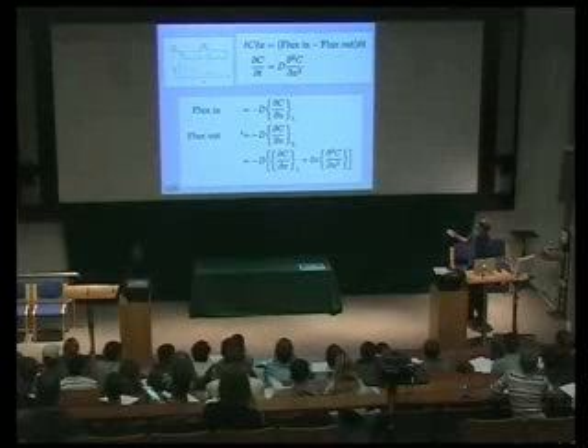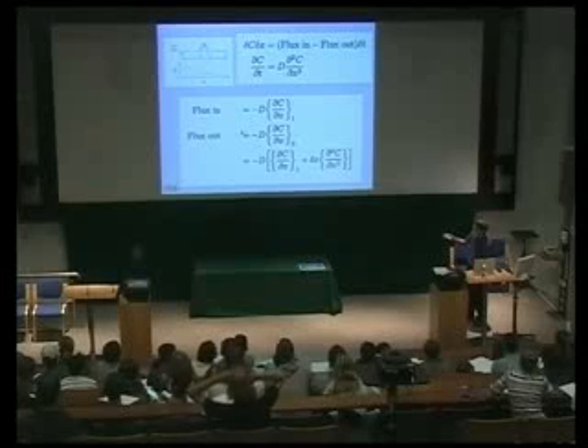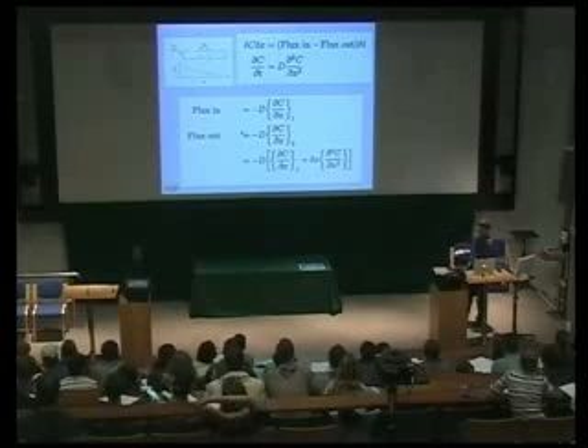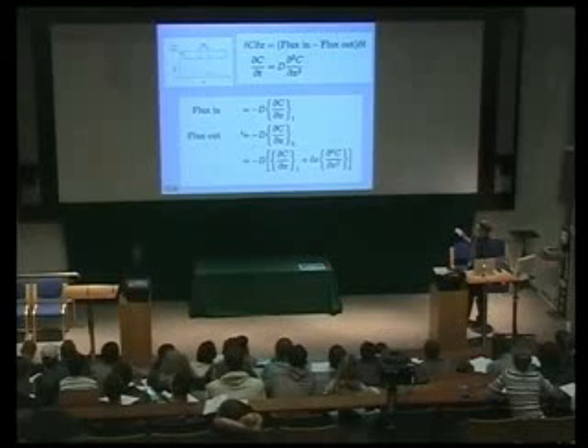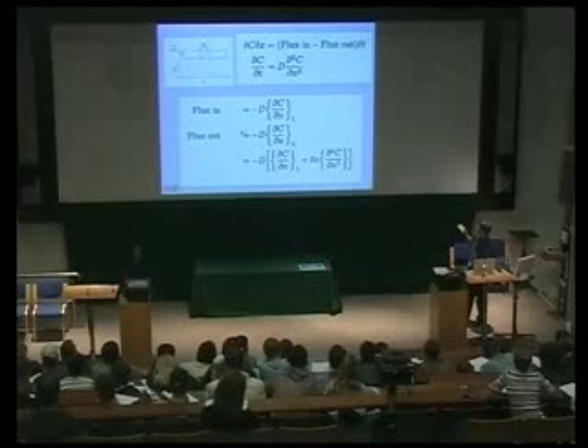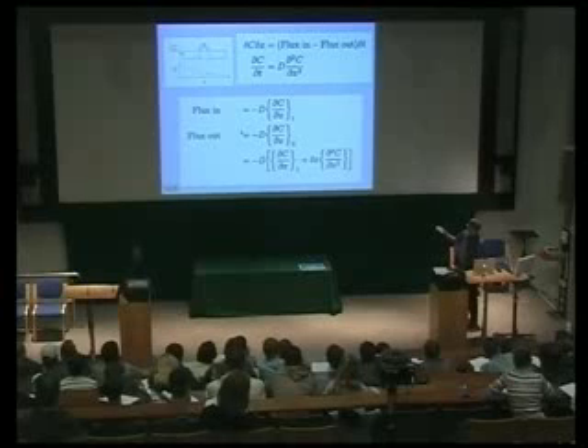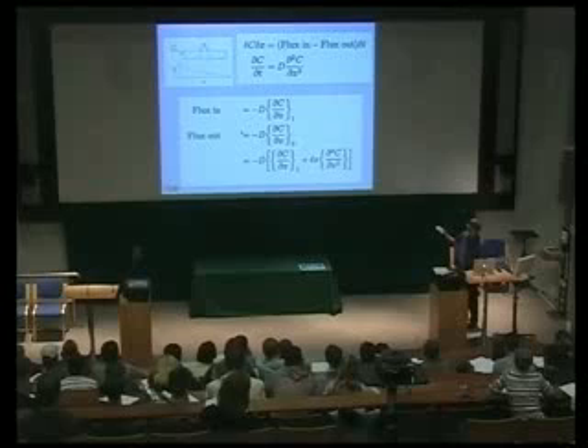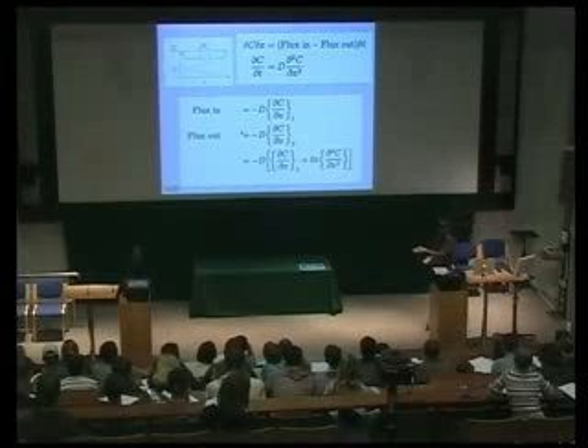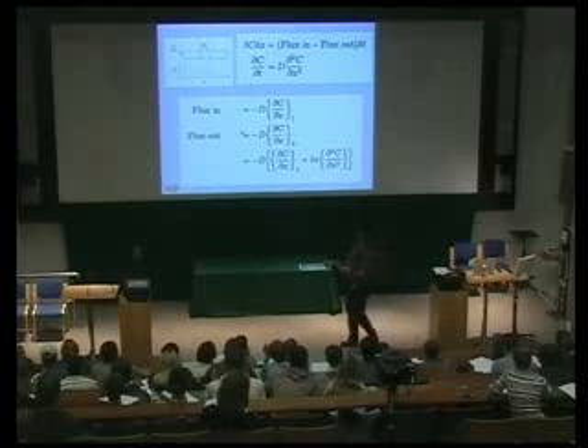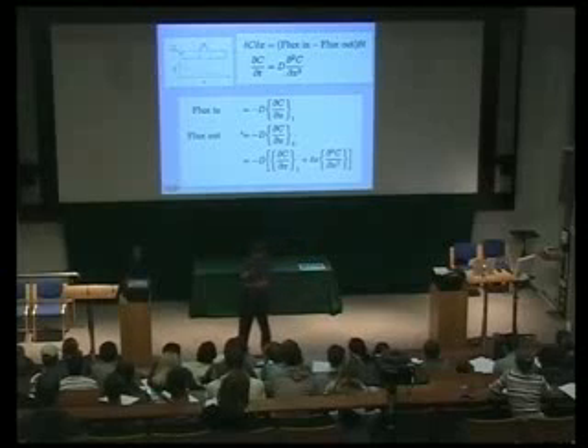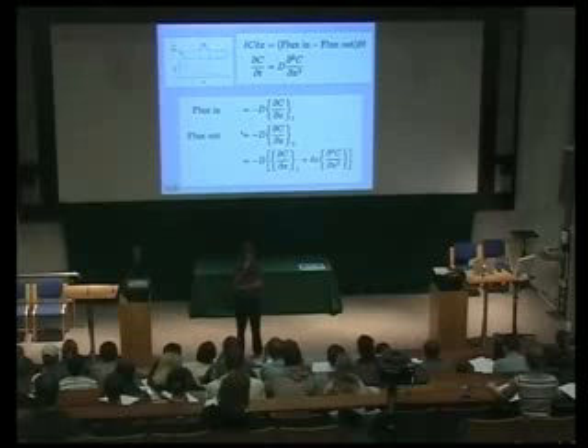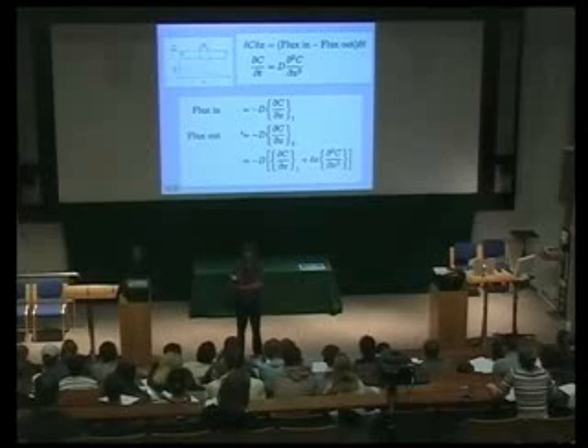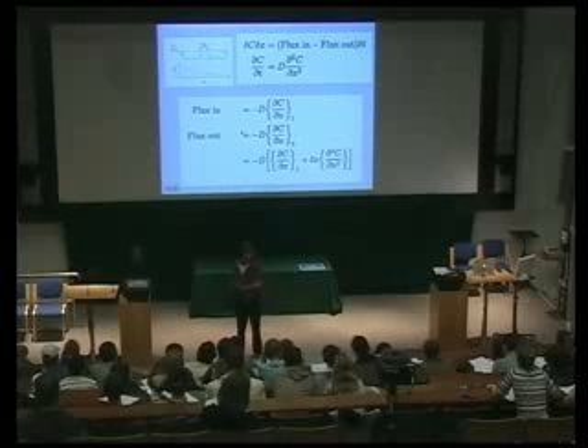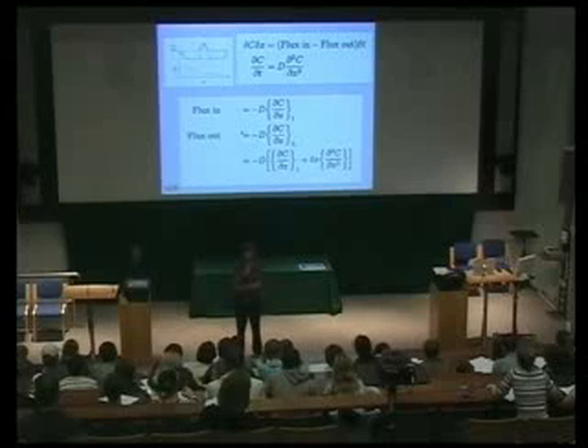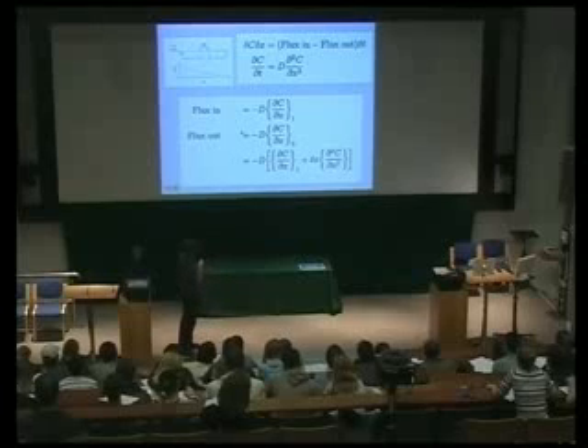Okay, so if I take my change in concentration in this region, delta C by delta X, that tells me how many solute atoms there are in that region. Flux in, flux out, the difference between those two multiplied by time balances with this side, and therefore I get the change in concentration with unit time being equal to D times the curvature of that line. Okay? So now we've got the concentration changing with time, and the rate at which that concentration changes depends on the curvature of that line. If that curvature, d squared c by dx squared, is 0, then I don't get any change in the gradient within that region, okay? Because there's no buildup or depletion of solute. So this is Fick's second law of diffusion.